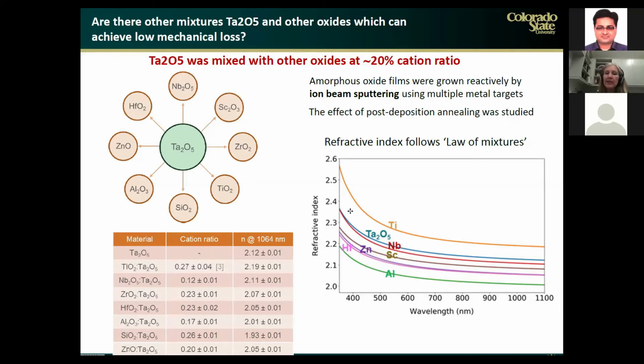And what you see here is how the refractive index actually changes when we add different other oxides to tantalum. So for example, when we add titanium, consistent with the law of mixtures, the refractive index at 1 micron increases. And when we add alumina, the refractive index decreases. And this again is another consideration in the design of the coatings, because we need a material that will have a large index contrast with silica to limit the number of layers that go into the coating structure. Because again, increasing the number of layers will increase the mechanical loss of the coating.